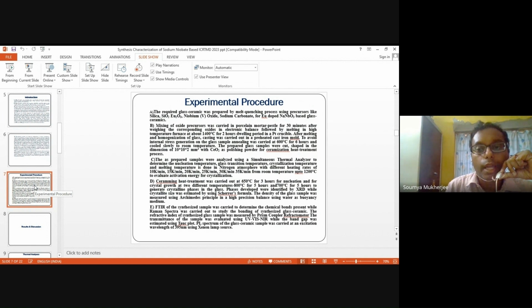They have been ground in an agate mortar and pestle for 30 minutes after proper weighing and put in the furnace for melting. We have utilized a platinum crucible for melting, and after melting, the molten system is put in a cast iron mold for casting. Now we have to be careful at this stage because we have to release the stress, as that stress may be detrimental. To relax the stress, some sort of annealing treatment is given, and after that it is cut into some dimensions and polished with cerium oxide.